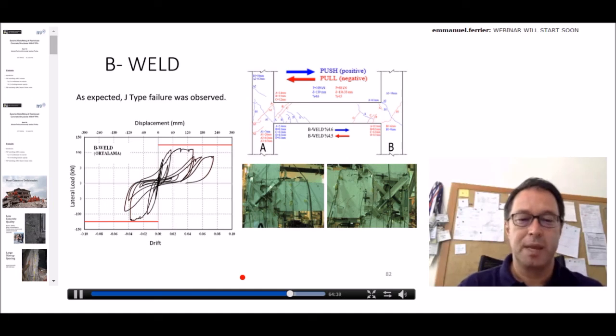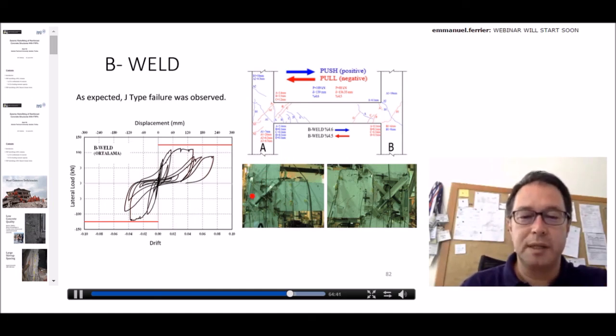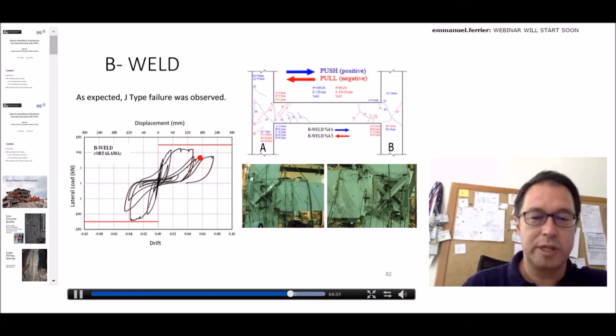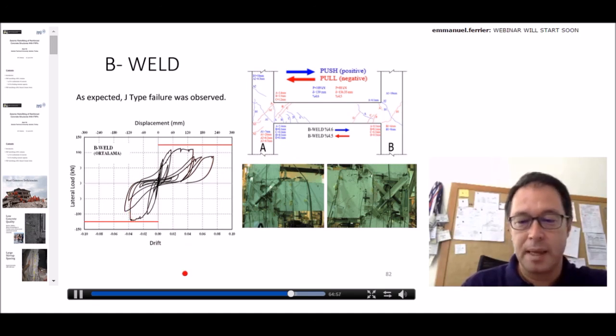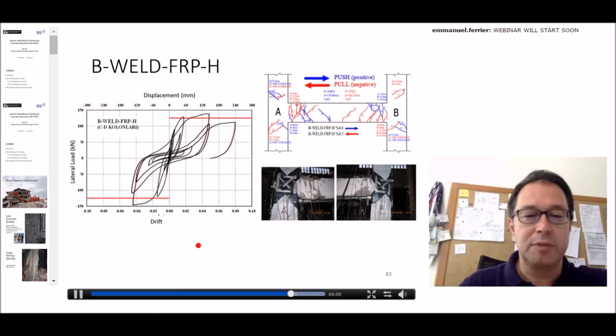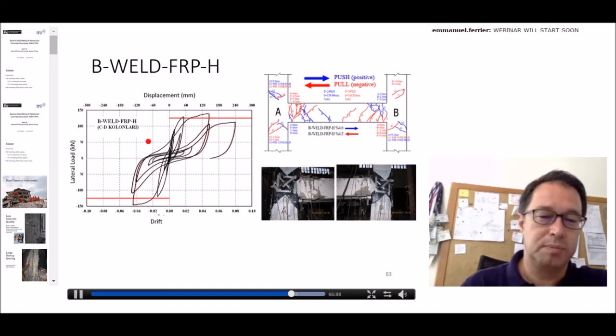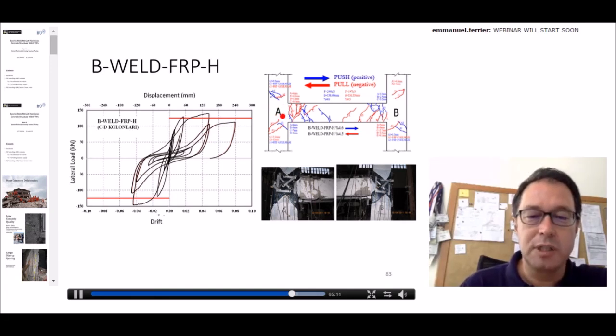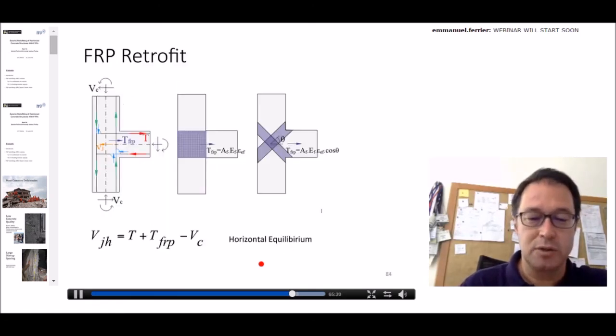And this is the one where we had the welding, but no FRP retrofit. Again, this time we had better strength, but less ductile behavior because of joint shear failure, increasing drift. Too bad, again. And finally, this is what we obtained when we have both precautions, avoiding slip and also improving the shear strength of the joint. So we could observe perfect behavior. This time, as you see, we didn't have any damage on the joint, and all the major damage was accumulated within the beams. And this was, as you know, the expected failure mechanism.